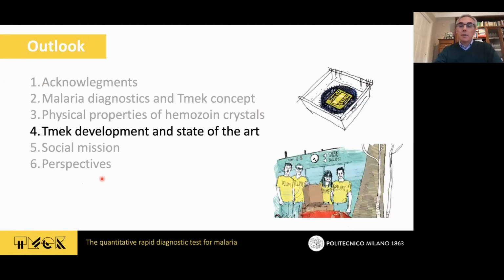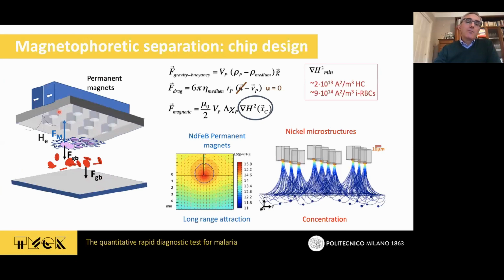And so we started with the engineering of the platform for using this idea of an external magnet and some concentrator to separate these particles, these corpuscles. This was the strategy. We decided to use some nickel posts as magnetic concentrators in the field produced by an external magnet. The idea is to use a combination of an external macroscopic gradient, which is able to attract or delay a little bit the sedimentation of the particles, and then use some concentrators in order to really concentrate the particles at the place where we are supposed to place our detector, which corresponds to our electrode. Just to show you what happens, in a simulation made using COMSOL you see exactly this concentration on the nickel post.